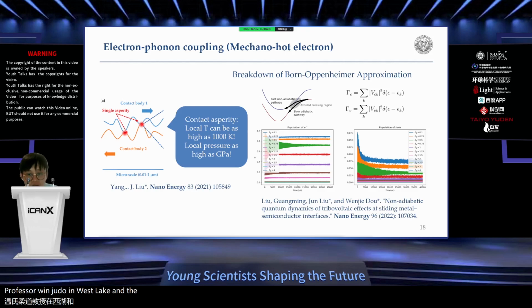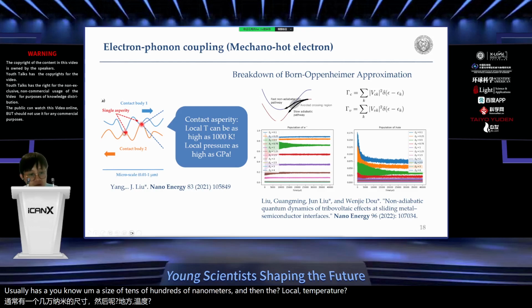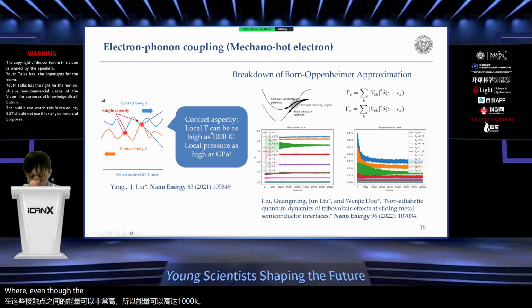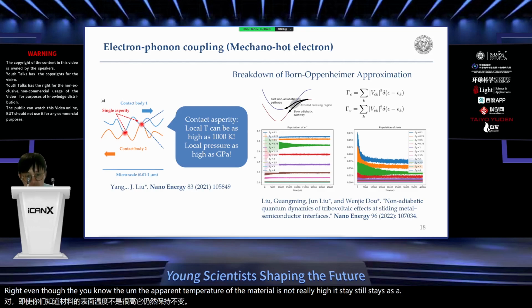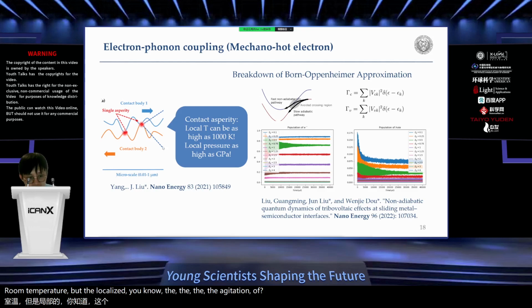And then the hypothesis we have is that right at the contact interface, you might have many contact asperities. These contact asperities usually have a size of tens to hundreds of nanometers, and the local temperature between those contact spots can be extremely high. It can be as high as 1,000 K, right? Even though the apparent temperature of the material is not really high, it still stays at room temperature, the localized agitation of atoms at a single asperity is very intensive.